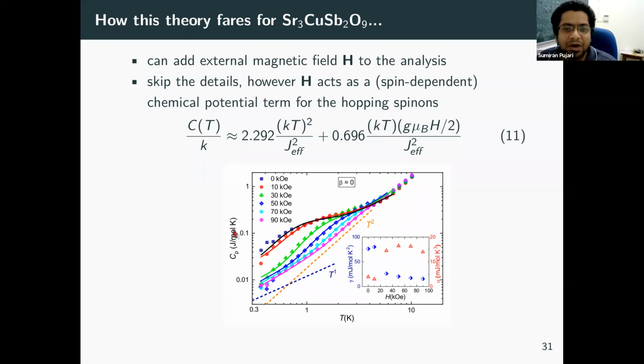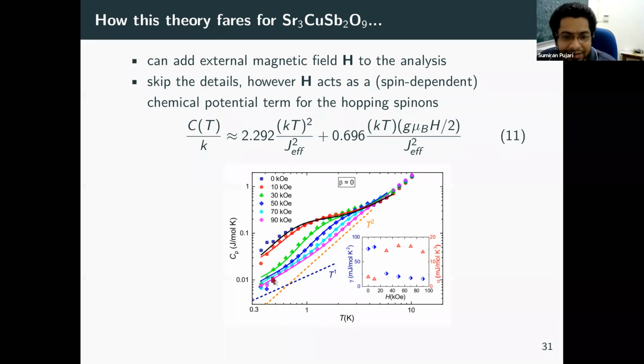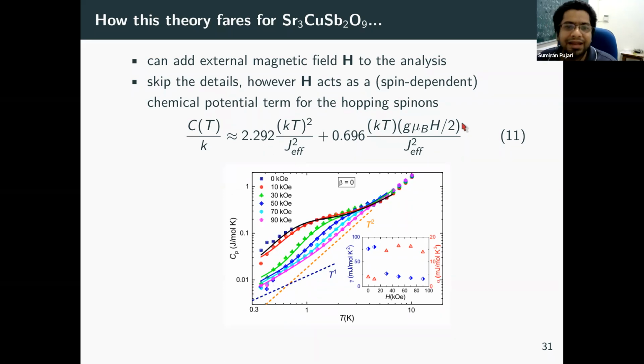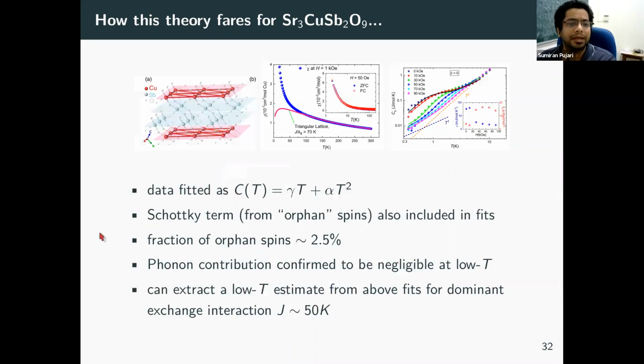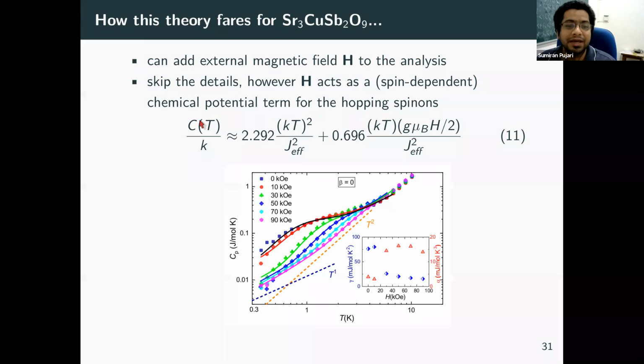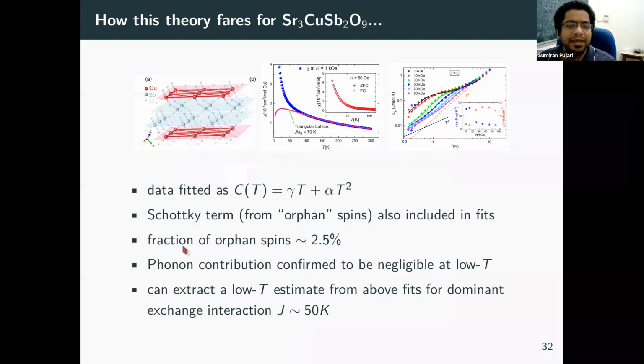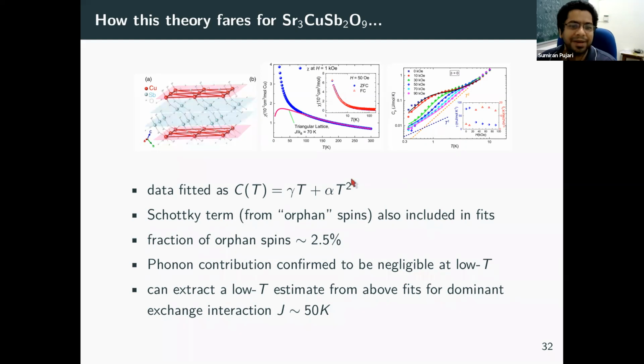But then later on, we found out that in the presence of a magnetic field, you get a linear component in the specific heat, and the linear piece also increases a little bit in the temperature range. And it really nicely worked out with this theory. So that is the showpiece result of the work, if you wish. How does this theory fare in some more detail? We fitted the data. The theory gives these numbers, but we don't take them too seriously; we just take this general fitting form. And with this fitting form, we can explain the data in a decent range of parameters.